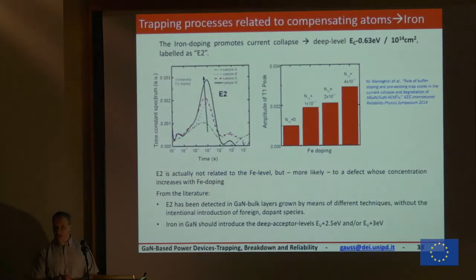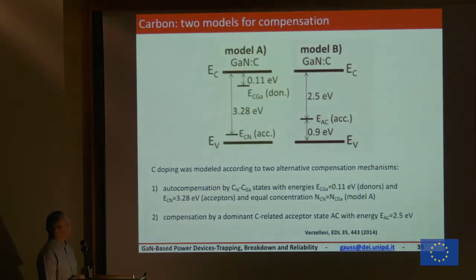Is this the end of the story? Not at all. For instance, here we had devices with a lot of carbon. Why don't you use iron? This is the other possibility to compensate. The problem is the same. You use iron in the buffer, and you have, in this time constant spectrum, a peak related to the traps. The higher the iron compensation that you need for a better breakdown, the higher the peak, the larger the number of traps. So the problem is the same, carbon or iron. My opinion is that the industry today prefers carbon for some reason, for less memory effect and so on. But in the end, you do have this problem. Let me skip this.